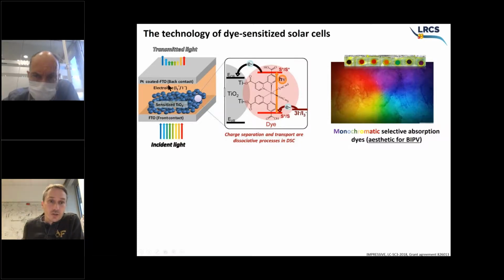It has two electrodes separated by an electrolyte, which can be liquid or solid. In our case, it's a liquid electrolyte. And everything happens here in the photoanode, where you have nanoparticles of anatase TiO2 nanocrystals, which are sensitized by an absorber, which can be an organic or organometallic absorber, whose role is to absorb the light and separate the carriers. If the LUMO and HOMO levels of the dye are well aligned with TiO2 and with the redox couple, we should have a separation of the carriers, so electron injection into the conduction band of TiO2.